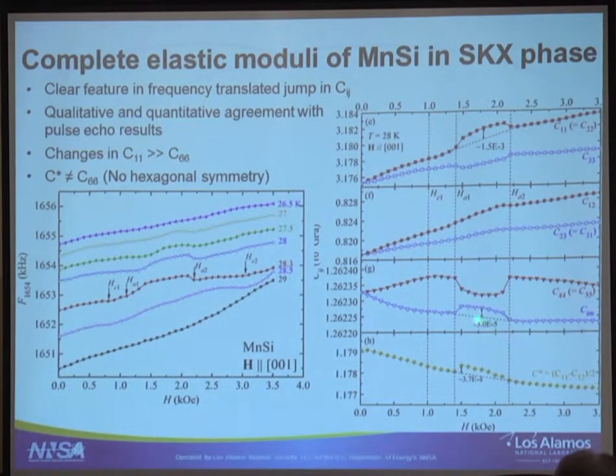Now, this raises a couple of questions. One is, is this little jump that I'm measuring here or here really the elasticity of the Skyrmion system? I'm measuring the whole elasticity. I'm measuring the whole sample. So actually what I'm measuring is the coupling between the Skyrmion and the ionic lattice. So we need more calculation to really see how the Skyrmion lattice couples to the real lattice.